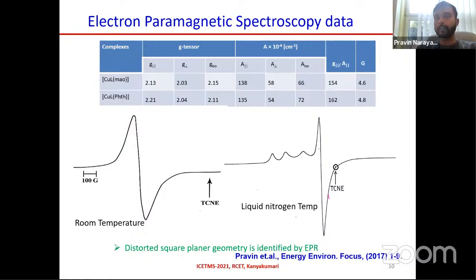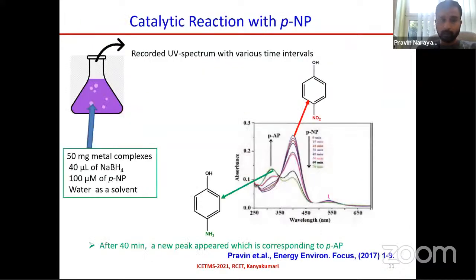So electron paramagnetic resonance spectroscopy is one of the best spectroscopic techniques to prove the geometry of the compound and the bonding nature of the complex. Based on the gyromagnetic ratio of free electrons, the g parallel and g perpendicular values, you can predict the geometry is a distorted square planar geometry, and the g value shows axial symmetry, which clearly states that there is no exchange interaction in the compound, so the compound is mononuclear in nature. So after careful structural characterization, we have performed the catalytic reaction with para-nitrophenol.